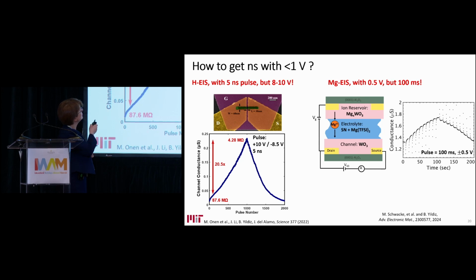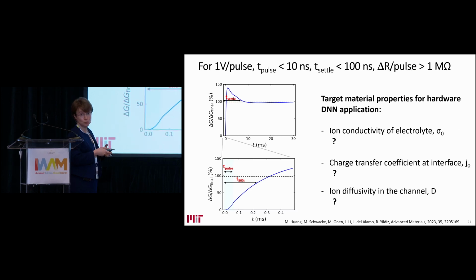So the goal is to be able to stay in this nanosecond regime, but program with very low voltage, so 1 volt or less. How do we get there with these electrochemical ionic devices? We don't know what those materials will be, but one has to identify what should be the ion conductivity of the electrolyte, what should be the charge transfer kinetic coefficients at the interface, and ion diffusivity in the channel, so that the device response, which involves a rise after, of course, the programming voltage and a transient to settle, can take place within less than 100 nanoseconds, which is consistent with the overall update of the network. So how do we get there?